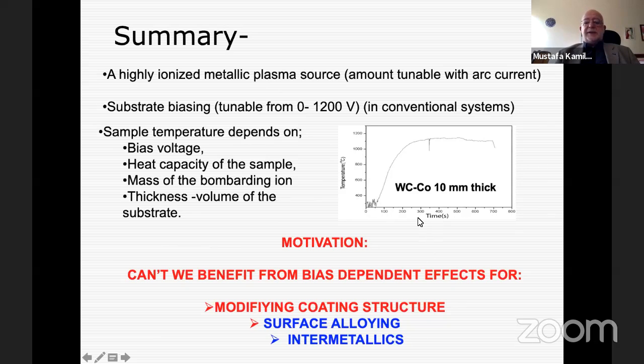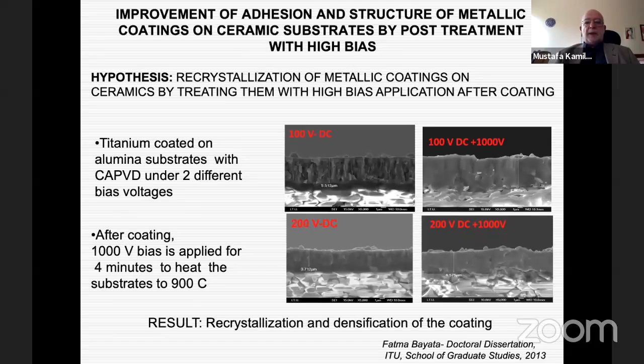Here you see an example. This is a tungsten carbide cobalt insert that is being subjected to cathodic arc chromium plasma by application of 1000 volts. As you see, you can increase its temperature in about 5 minutes to about 1,100 degrees. So this is a very powerful tool for heating the substrates. So we started to try to benefit from this effect.